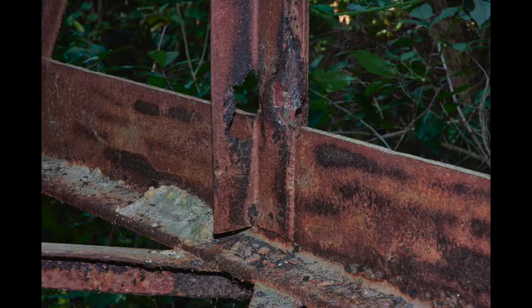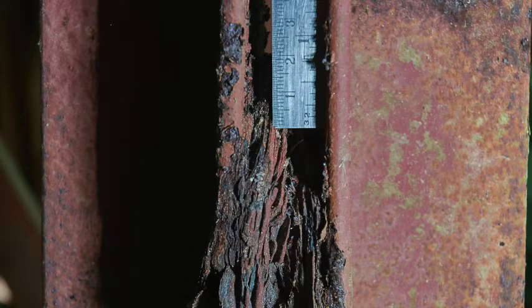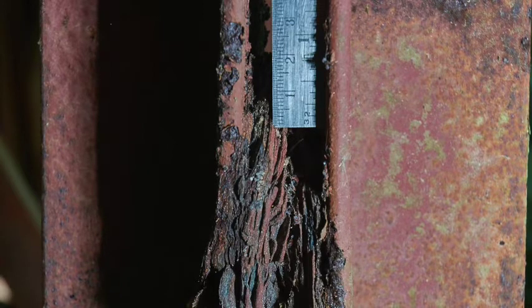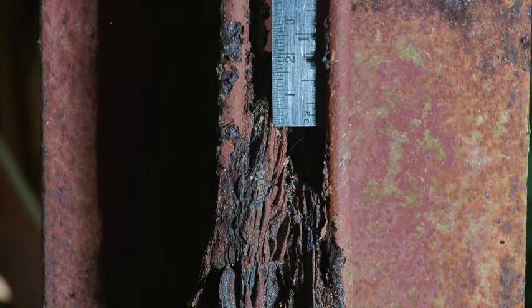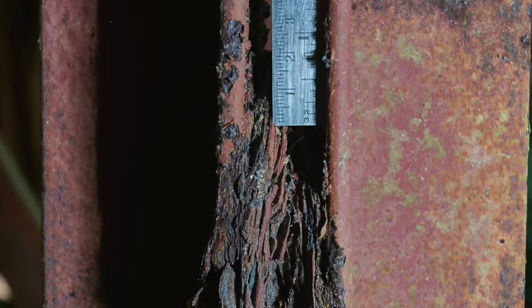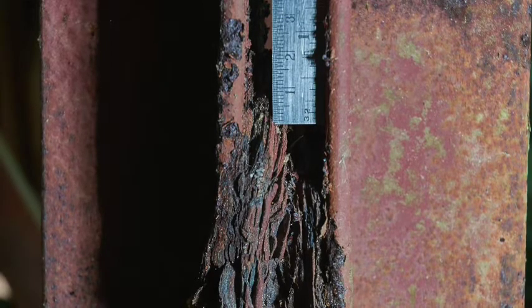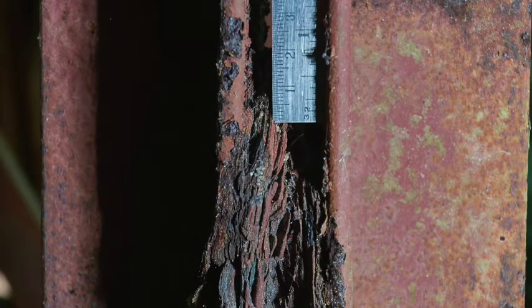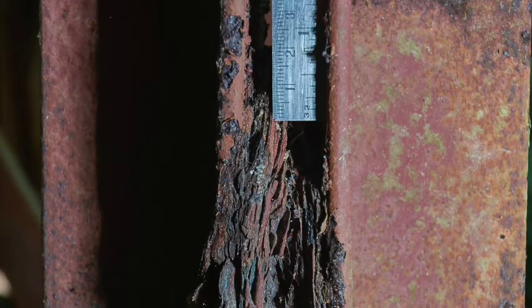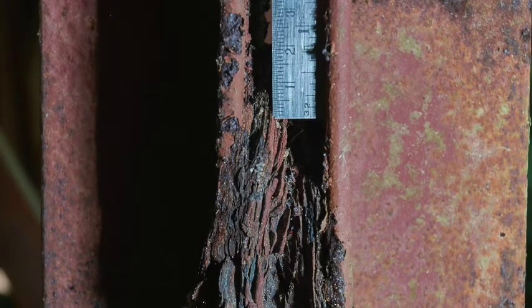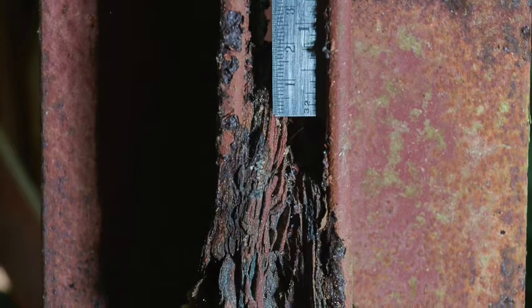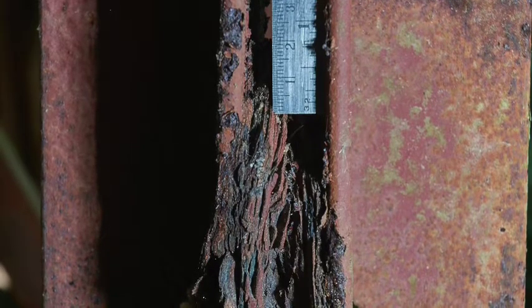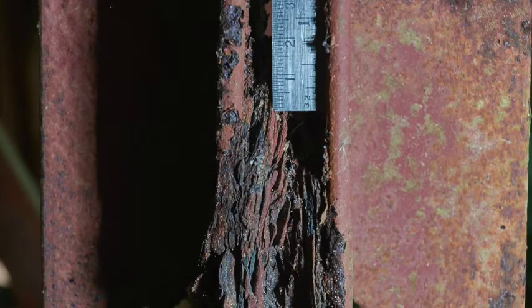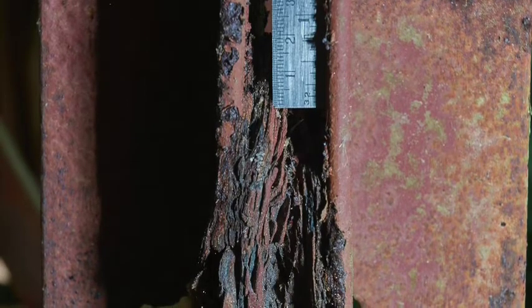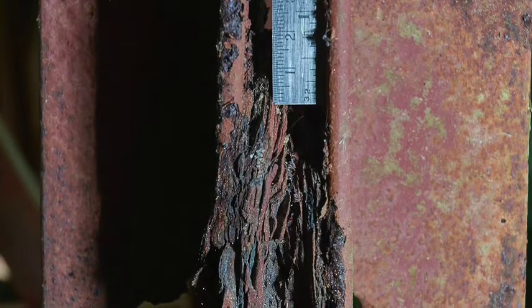So looking at this particular section in more detail, this is a ruler here, which is about 10 millimeters. So the steel I've measured is 10 millimeters thick. And we're looking at frame 15 March 28. Now this again, to me, looks like paper mache. Or, no, it actually looks like puff pastry because you've got so many different layers. So what's happening in there? Why is that steel suddenly... Crevice corrosion, and it's occurring for the reasons that we've discussed.